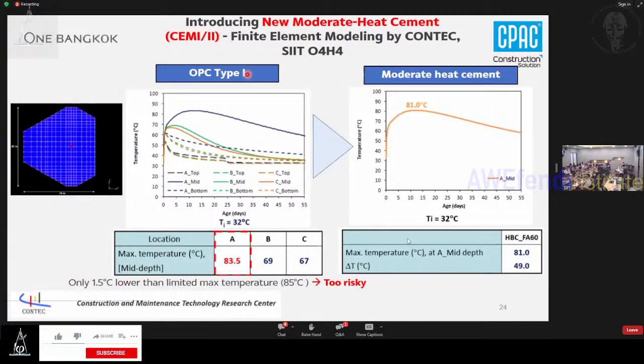Moreover, we use fly ash 60%, and we use moderate heat cement combined with the fly ash 60% as well. So after that, we calculate the model again. We get the peak temp around 81 degrees Celsius. The owner became happier about this because the number is reduced.